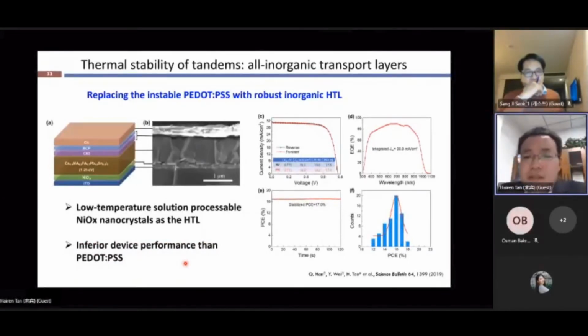So even from the early year of 2019, we were thinking about how to replace this PEDOT layer with more thermally stable materials, such as the nickel oxide nanocrystal film. We can make good performing solar cells, but the device performance is still not as good as what we obtained in the PEDOT-based devices. And I think in the future, we still have to do much work on this.